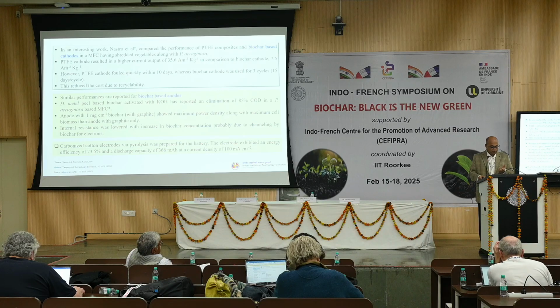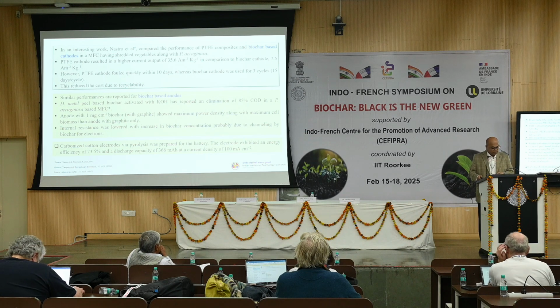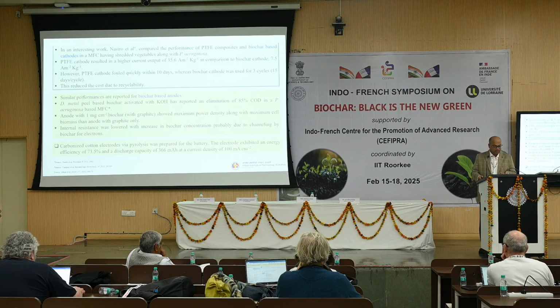What they observed is that the internal resistance was lowered with an increase in the biochar concentration. What they say is that it is probably due to some channeling effect during the transfer of the electrons inside the biochar material. And in another work, carbonized cotton electrodes were produced using pyrolysis for battery applications, and the electrode exhibited an energy efficiency of 73.5% and also a good discharge capacity.